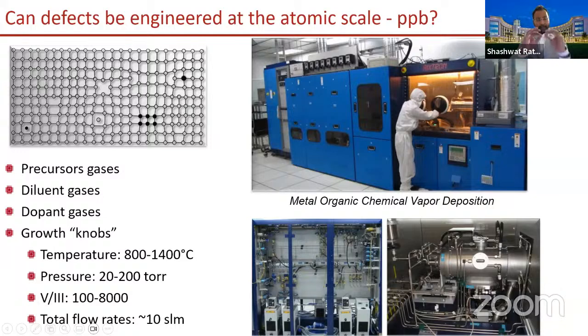And I mentioned that these defects play a fundamental role in controlling the properties of semiconductors. So I mentioned this defect that you see in the top right of this cartoon, where we are substituting a foreign atom in the host lattice. This is known as doping, but it need not go on that site all the time. It can go in a site where we do not want. We can also knock out an atom from its site, which is called a vacancy. So there can be a zoo of defects that you create in the material, and each of these defects has a profound impact on the material properties.